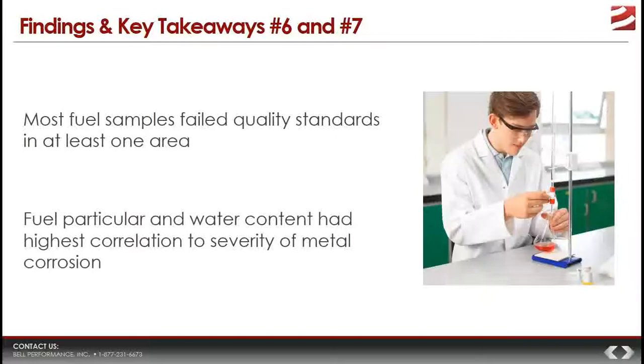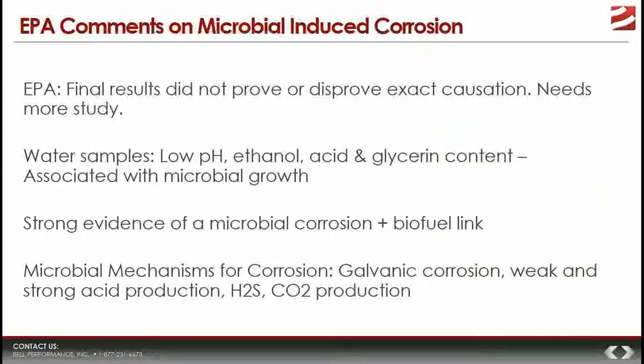So let's restate that to make sure that we're clear. If you went out to your storage tank and took a sample of diesel fuel and then you shipped it off to be tested and it came back and said, yeah, it passed this, and this, but oh yeah, for the water and sediment test, it fails. It's got excessive water content and it's got excessive sediment content. What that would tell you, apart from the bad news that your fuel is not in spec, is that there is a high correlation to the possibility that your storage tank has severe corrosion problems going on in it right now. So those were the 7 key takeaways that the EPA had coming out of the results of their study.